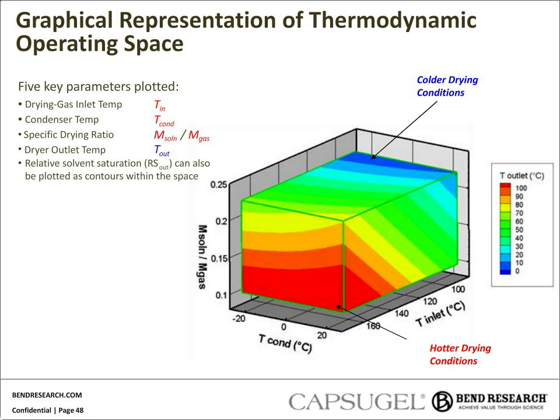So switching back to thermodynamic parameters, this is the same graphical representation of the mass and energy balance or thermo model that we showed previously. In this case, we've added a third axis for the condenser temperature, which is the additional key parameter that must be considered at large scales. So again, we're showing dryer inlet temperature on the x-axis, condenser temperature on the y-axis, and the specific drying ratio or feed rate on the z-axis with contours of outlet temperature within the box.